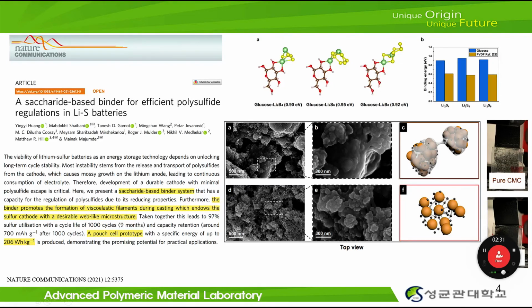Here is an example. This paper reported a cellulose and glucose composite binder to inhibit the shuttling effect, because the glucose can combine with the polysulfide very tightly compared with the conventional CMC binder. Also, the glucose and cellulose composite binder forms a very porous network on the cathode side, so it is good for the lithium ion transport, as you can see in the scheme in figure F. And the composite binder has very high adhesive property on the current collector, so the structure of the cathode can be stable during the cycling.